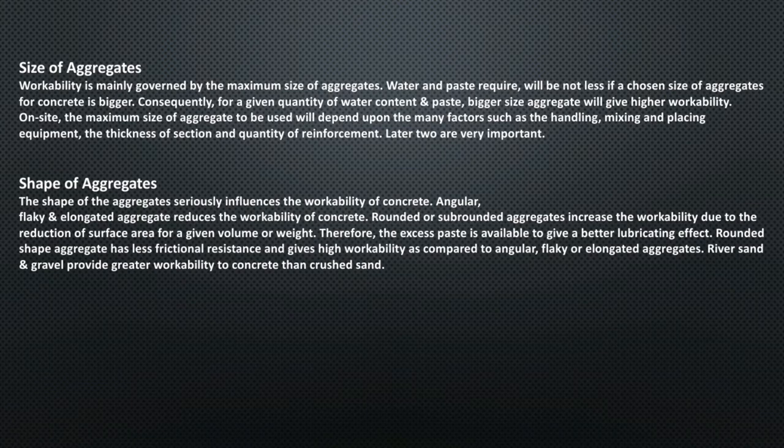Factor number three is shape of aggregates. The shape of aggregates seriously influences workability. Angular, flaky, and elongated aggregates reduce the workability of concrete. Rounded or sub-rounded aggregates increase workability due to the reduction of surface area for a given volume or weight, so the excess paste is available to give a better lubricating effect. Rounded shape aggregate has less frictional resistance and gives higher workability compared to angular, flaky, or elongated aggregates.